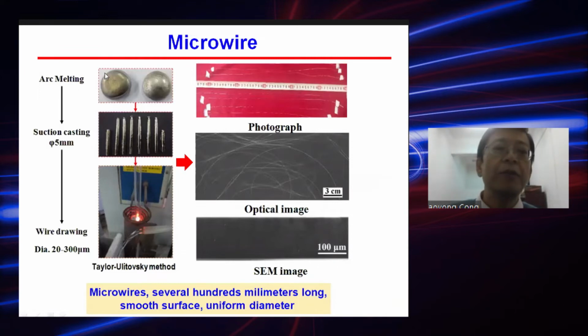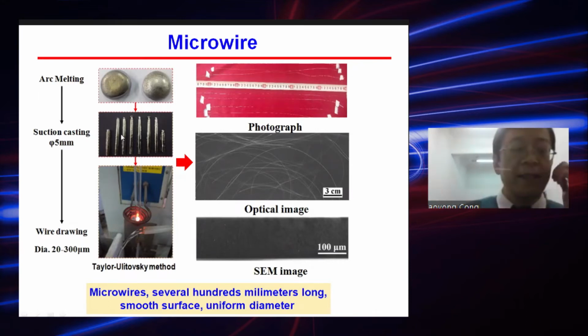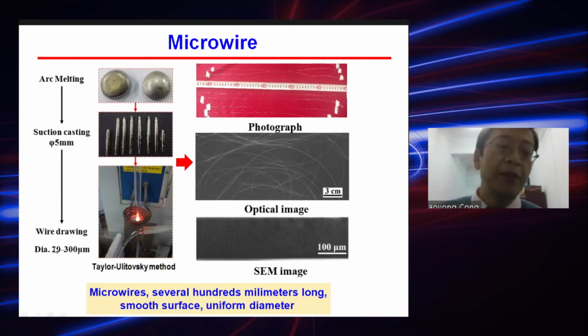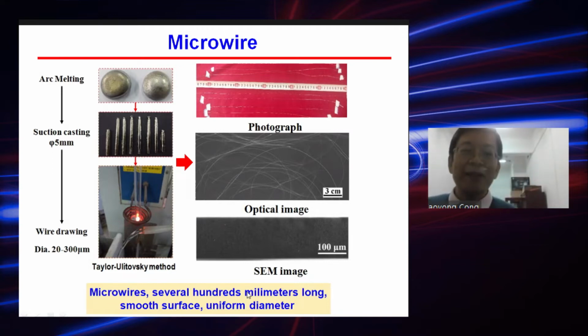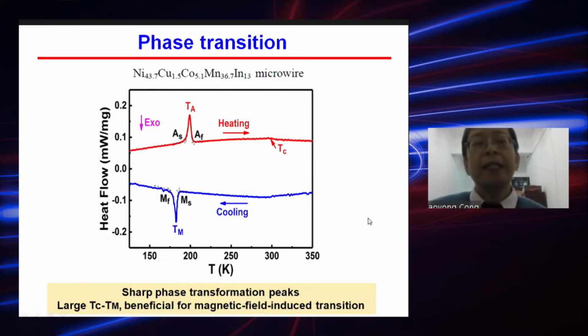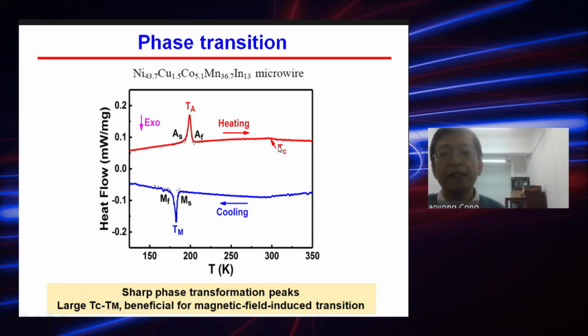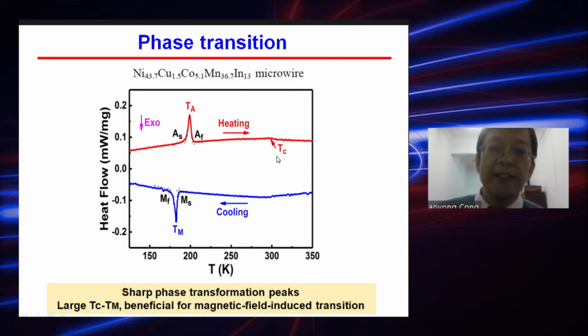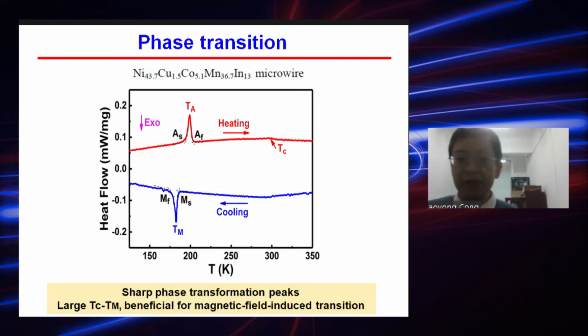So we first use arc melting to prepare the button ingots, and then we use suction casting to get the cylindrical rod. And then we use this Taylor method to draw wires, and the wires can have a diameter between 20 and 300 micrometers. And the microwires can be several hundreds of millimeters long, and have a smooth surface and a uniform diameter. We first tested a composition with nickel, copper, cobalt, manganese, and indium. And this microwire shows sharp transformation peaks. And also we can detect the Curie temperature in the DSC curve. We see that there's a large difference between this Curie temperature and this transformation temperature. This is quite beneficial for magnetic field-induced transition.